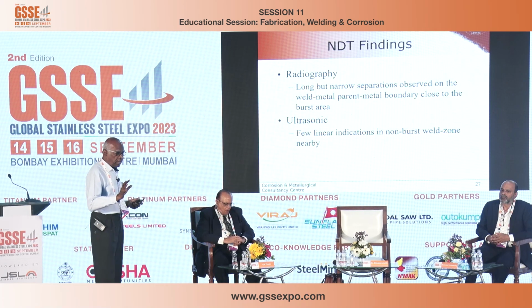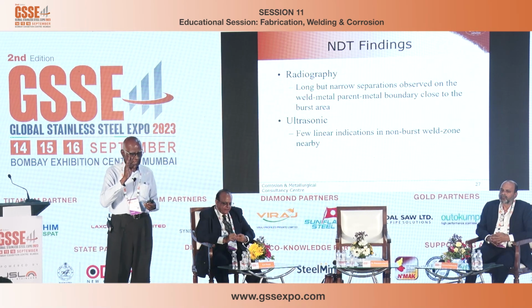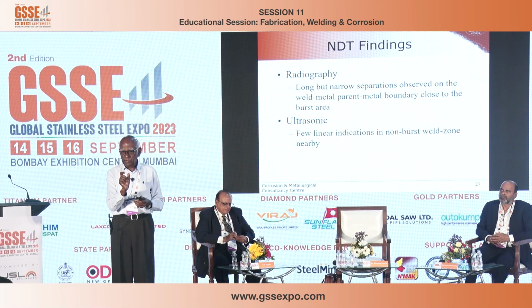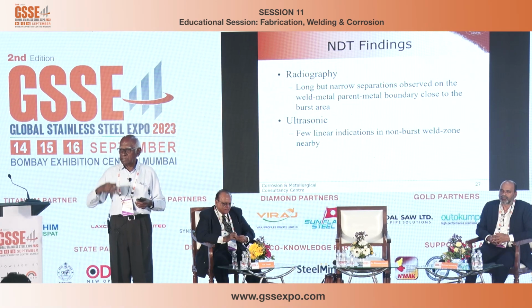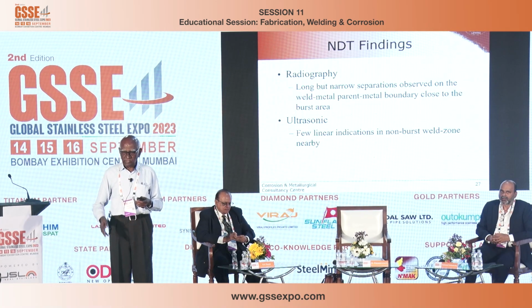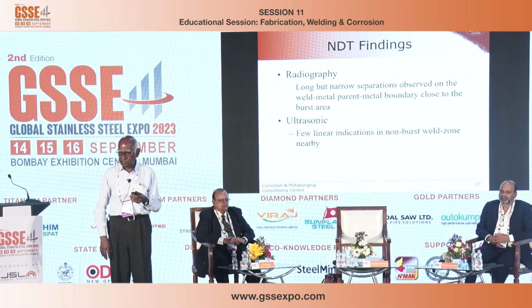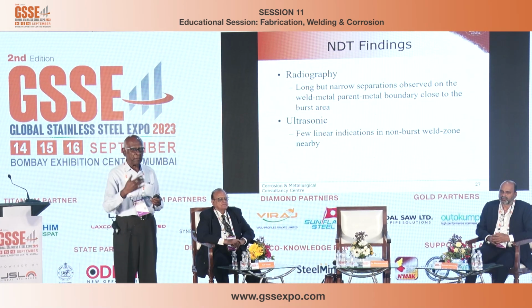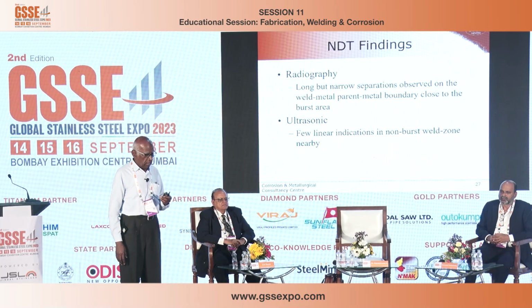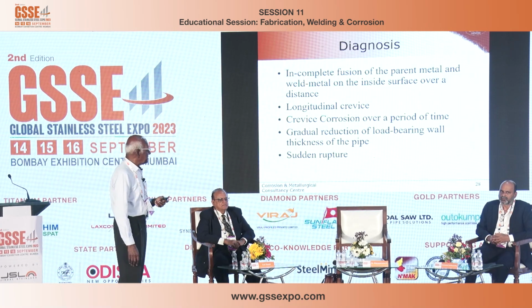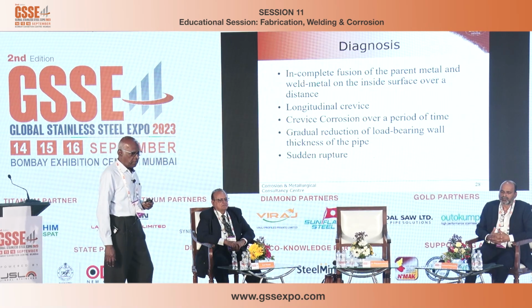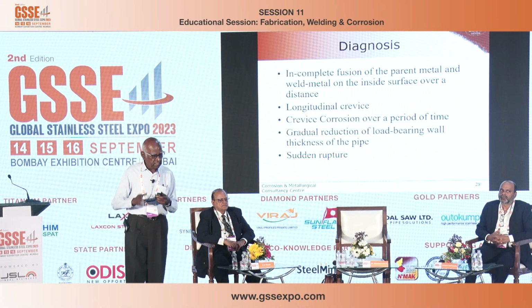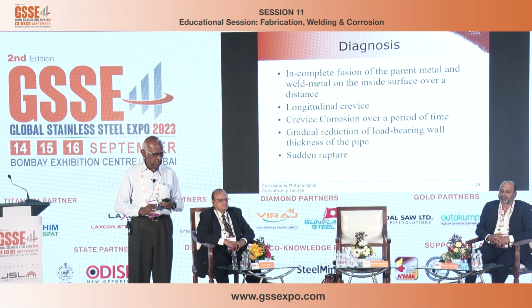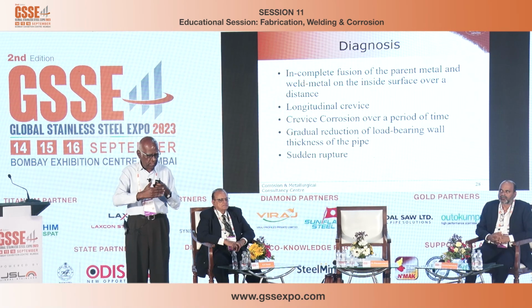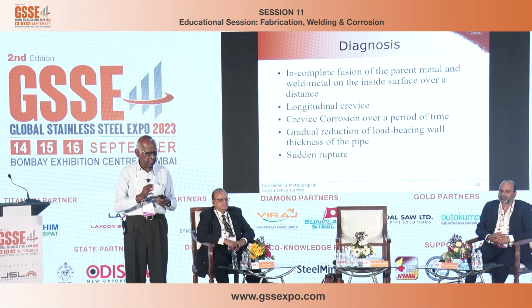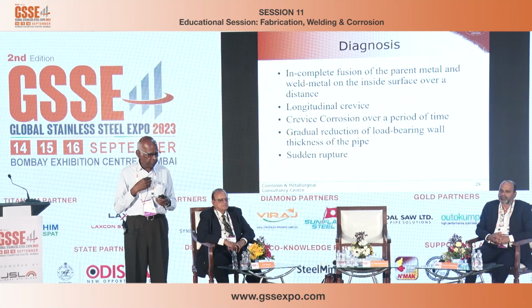Radiography and ultrasonic showed definitely there is a partition between the weld metal and the parent metal, but that was assumed not to make any problem. So the third party inspector passed the pipe. And the diagnosis: incomplete fusion of the parent metal and weld metal on the inside surface over a distance. That formed a longitudinal crevice corrosion.